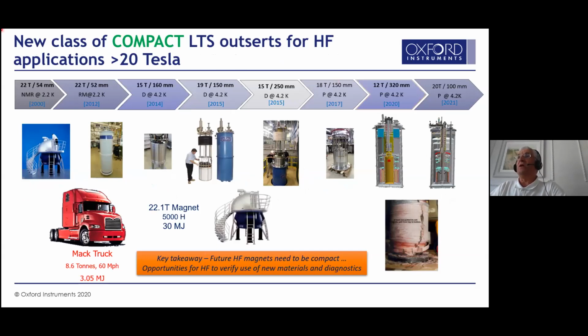So that has basically led us to a new class of high field systems, compact in size, starting with 15 Tesla, 160 millimeter at 4K, leading to a 19 Tesla 150. This is one of the first high field systems operating at 4K that we think, with the high JC wires, we can now develop systems running at 4K with wider bores without the need to use pumped helium, which makes the system more complex to run and very expensive. Secondly, we want to make sure that our designs can be adapted for cryogen-free systems as well. These are now systems currently in production as standard products, and they can vary from 19 Tesla 150 to 20 Tesla 100 millimeter bore at 4K.